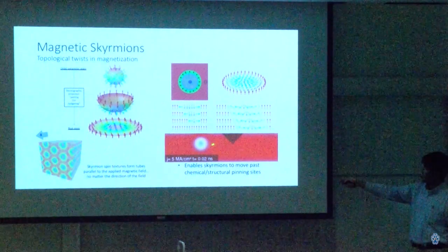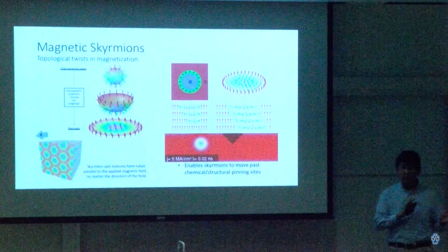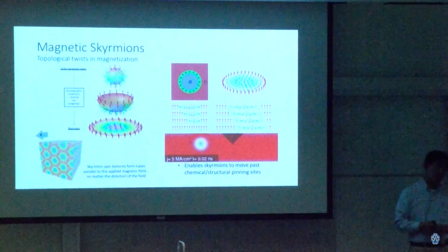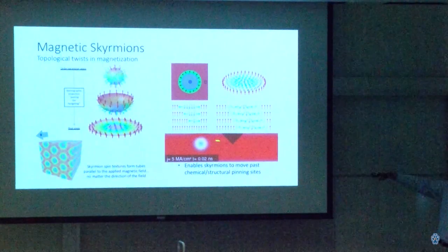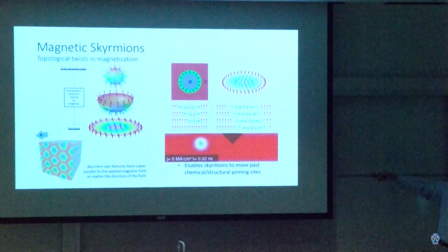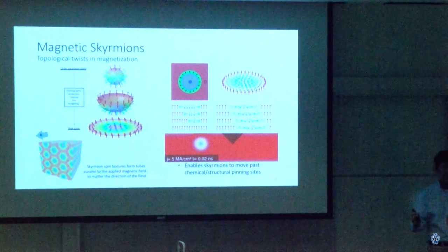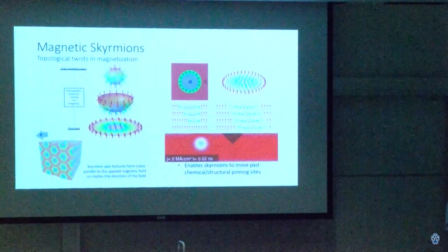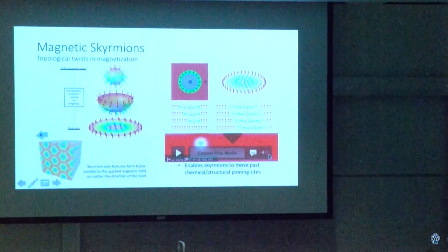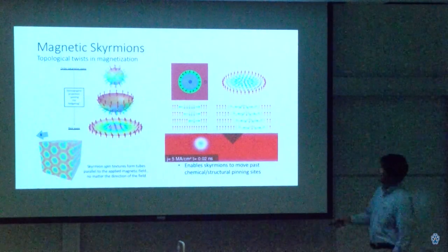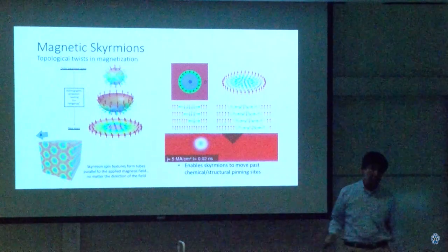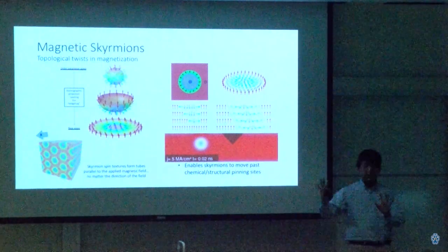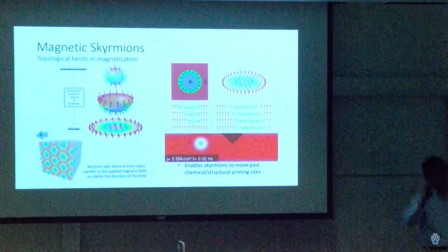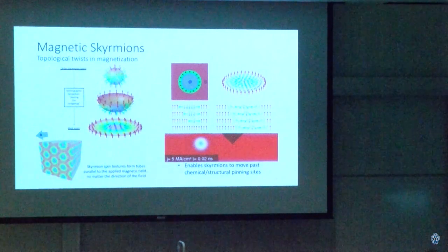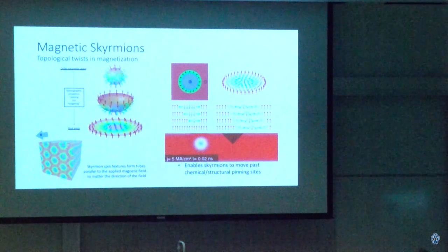Say, for example, we had a skyrmion in the magnetic material, and you were to drive it from, say, left to right using an electric current. With a bubble, it might get caught on this structural defect and then shrink away to nothing or just stay there. That should play. Oh, cannot play immediately. That's the beauty of PowerPoint. So, on the other hand, if this were a skyrmion, what you would have seen is the skyrmion hitting that defect, rolling underneath it, and continuing on, out of the frame of view, just like in the camera.